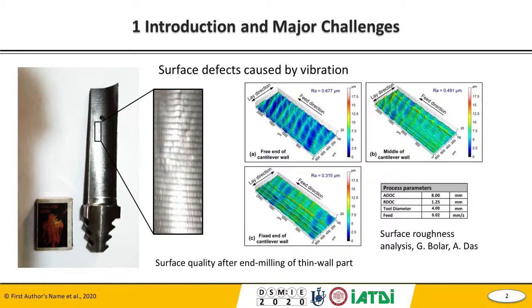There are factors to consider in machining, and the first one is vibration. On the left side you can see defects: rough feed lines and chatter marks. On the right side, an example of surface quality obtained from profilometry analysis of a thin-walled part. These probes were taken from the fixed end, the middle, and the free end of the wall. It shows that the roughness of the surface increased towards the free end of the wall. It proves that stiffness distribution isn't uniform. And in these terms, the support of such critical zones is interesting to investigate. Next slide, please.